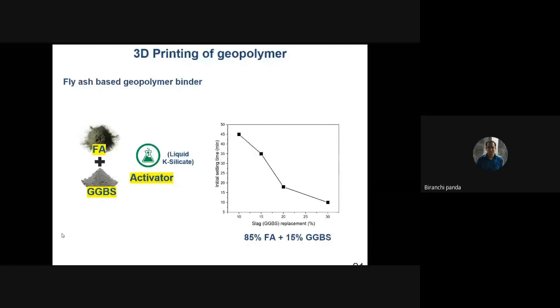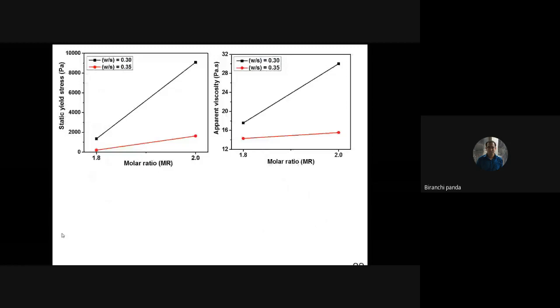because here we don't need a lot of water. Instead of water, we need an activator, that is potassium silicate, and we use this potassium silicate to make the concrete material, and that too using byproducts like fly ash and slag. Those are coming from different steel plants. And we investigated how we can design a printable mix using this material.